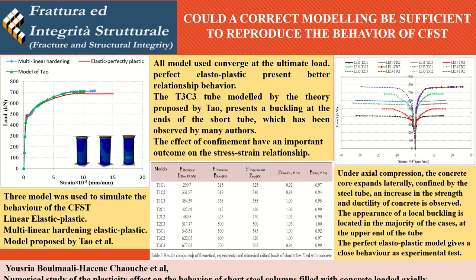The majority of the vertical compression strains show plastic flow with large strains reaching an average of 30%. We note, however, that the T3C1 and T3C2 tubes gave lateral and vertical strains of the same order.